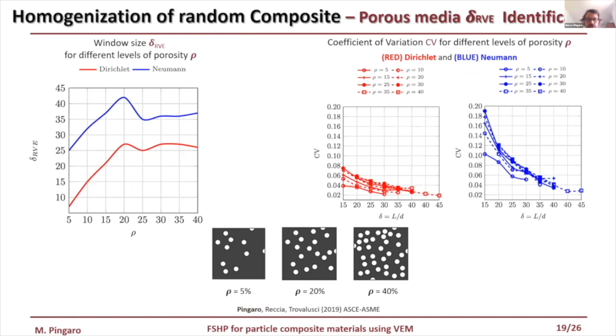And concerning the dimension of the representative volume element with respect to the porosity, it increases linearly in the range of 5 to 20%, after that it decreases, and after more or less 25% it became constant.